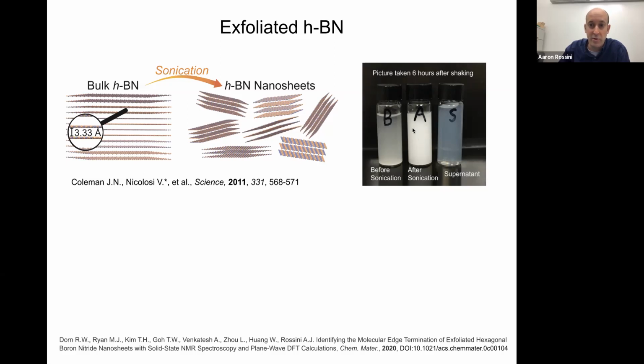If you centrifuge the sonicated boron nitride nanosheets down and just collect the small nanosheets from the supernatant, these sheets are colloidally stable. So this suspension will stay cloudy for weeks or months if you leave it, and there are no surfactants added here.